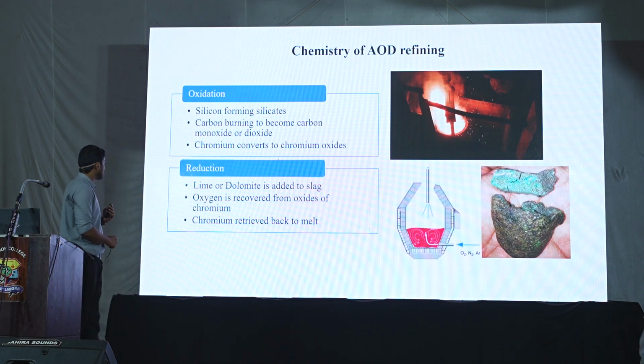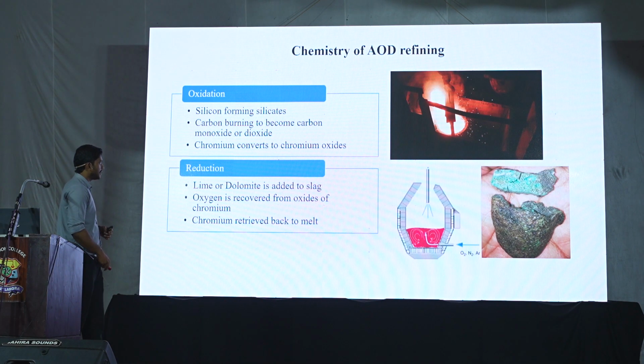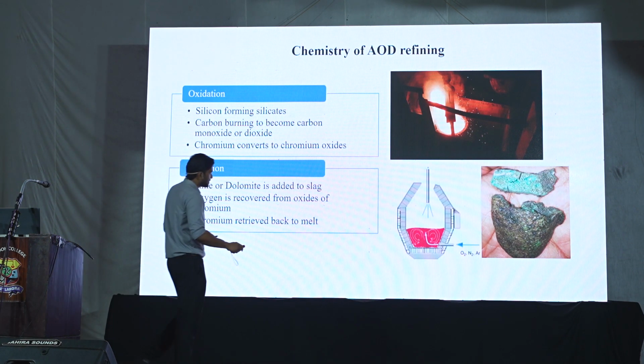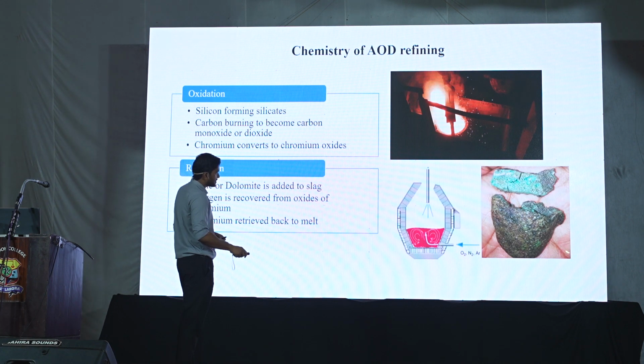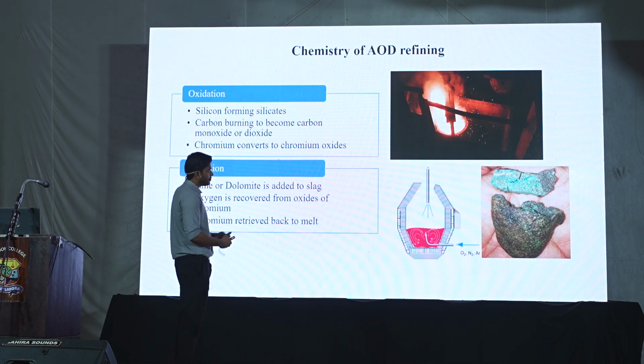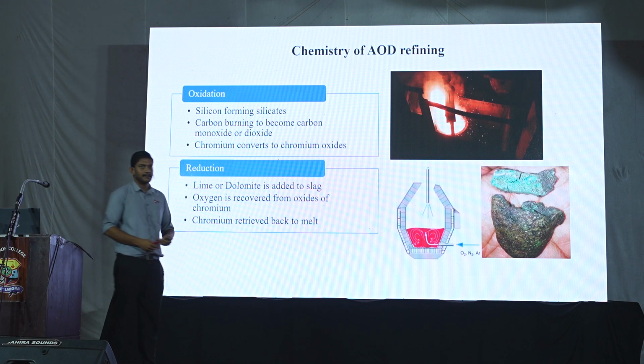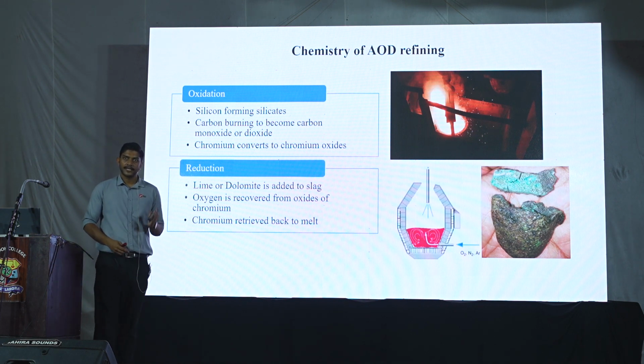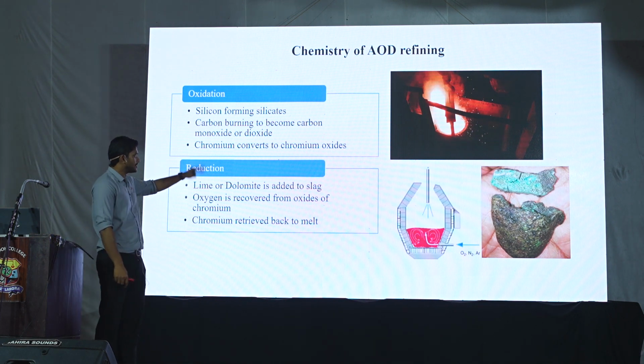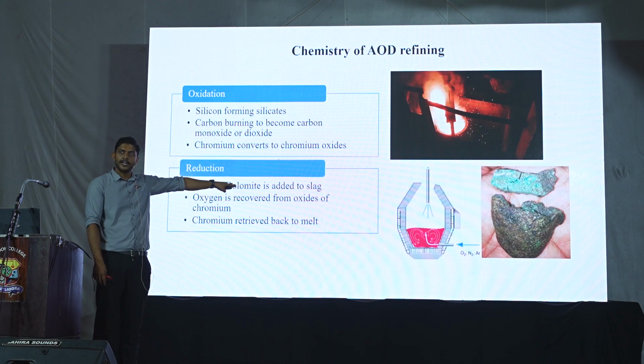So first silicon will be removed. This carbon will be gone as carbon dioxide, it goes out, and basically only chromium remains in the slag. To know whether the stage is reached, we'll just take the slag out, cool it in water, and break it off. You can see the color, it's kind of green. So we can say that chromium is there in it, everything else almost gone. That's the meaning of that.